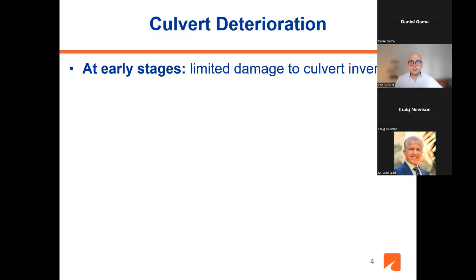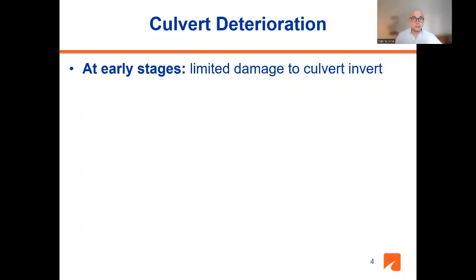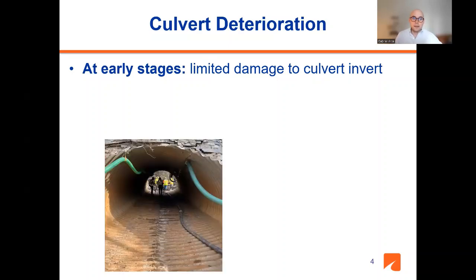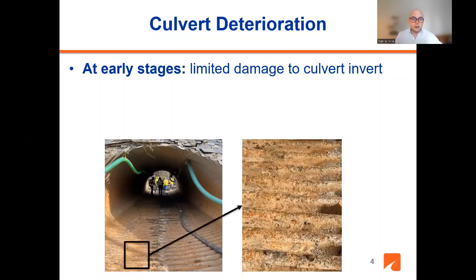How does this deterioration occur? At early stages, only limited damage occurs at the invert of the culvert. The invert is the bottom portion of the culvert. Of course, that's the area where the water is always flowing and therefore it's more susceptible to damage. This is an image of one of the culverts here in Virginia with some minor deterioration of the bottom portion of the invert. Here you can see a zoomed-in picture of this deterioration. As you can see, you start losing a little bit of the surface of these culverts.